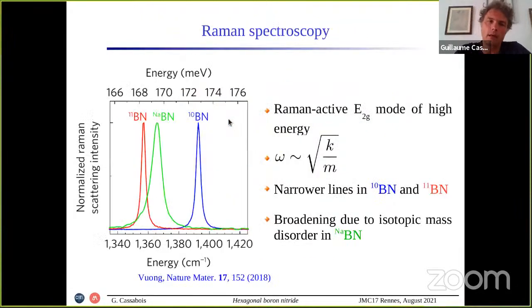The first characterization was Raman spectroscopy, which is quite obvious because the eigenfrequency scales like the inverse of the square root of the mass. So by changing the mass of the isotope, we can tune the phonon energy. Here you have the Raman spectrum of B10, B11, and B natural. For the lighter isotope, we have the higher energy of the phonon, so this is the first characterization. We also have some narrowing of the line because we suppress isotopic mass disorder, as is the case in boron nitride with the isotopic mixture.